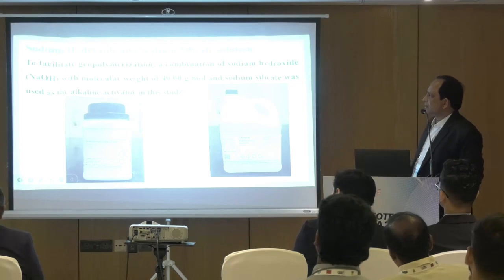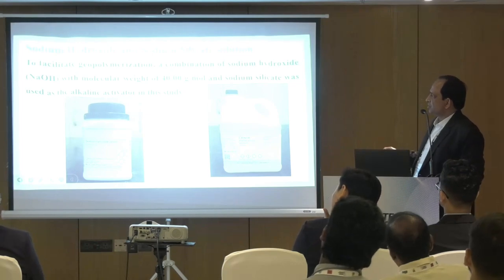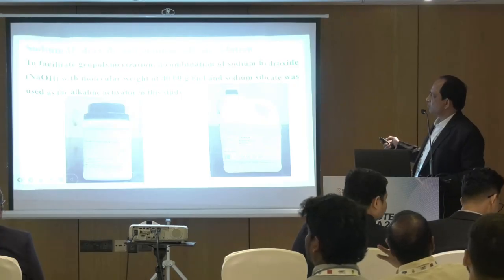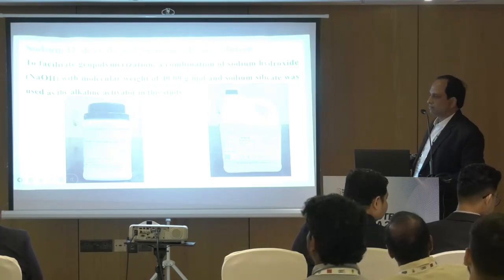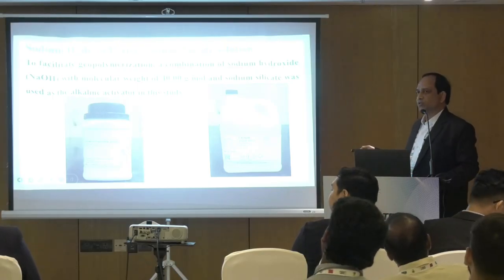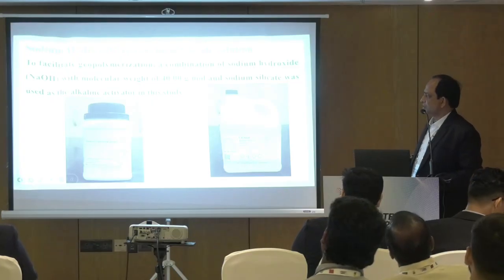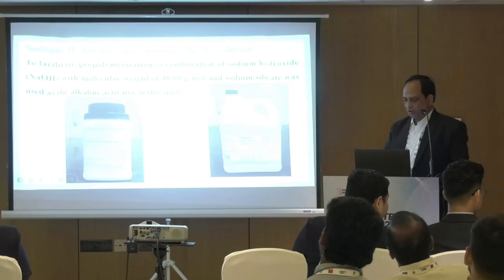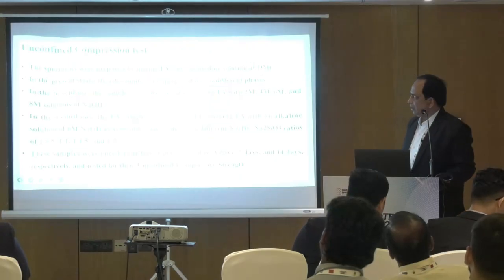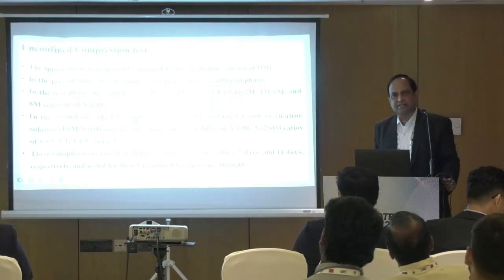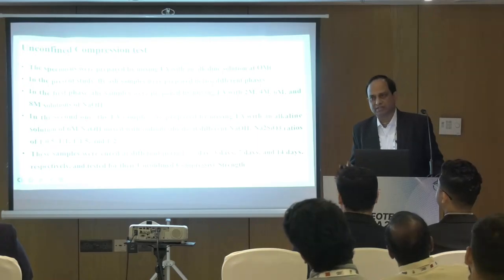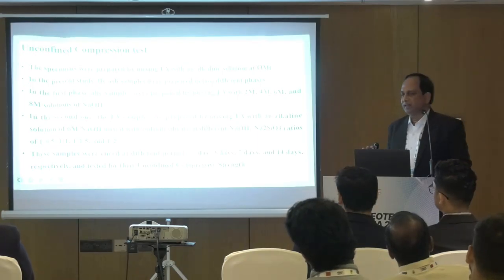Then we have taken up two materials based on literature with so many publications. For geopolymerization, we have gone for a combination of two things. Of course, we tried initially only sodium hydroxide independently with some molarities. And then we thought of adding sodium silicate so that long-term effects will be there. So we have taken sodium hydroxide and sodium silicate solutions for this. And as a basic test of getting the strength, we have gone for UCS, which is a very easy and very comfortable one.